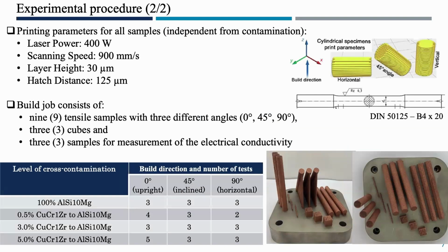So the printing strategy was twofold. The first one is the different levels of cross-contamination: without contamination, 0.5% contamination of copper to aluminum, 3% copper to aluminum, and 5% copper to aluminum, plus another variable was also the build job. This is upright, 45 degrees, and horizontal.